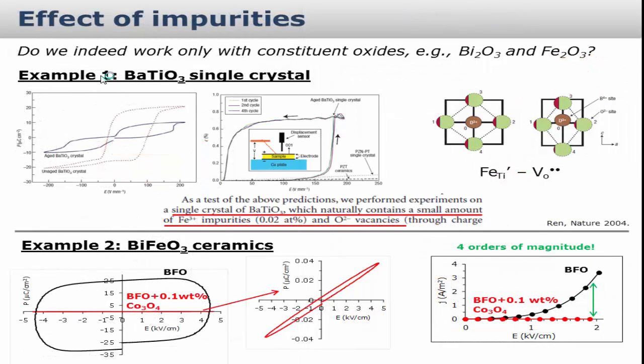So I start with these impurities and phase diagrams. In general, the effect of impurities on the properties of ferroelectric ceramics is well known. I'm showing here two examples. One is this barium titanate single crystal from Ren's paper, in which he showed this large strain that is reproducible,